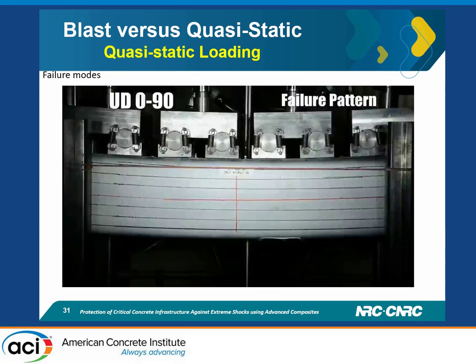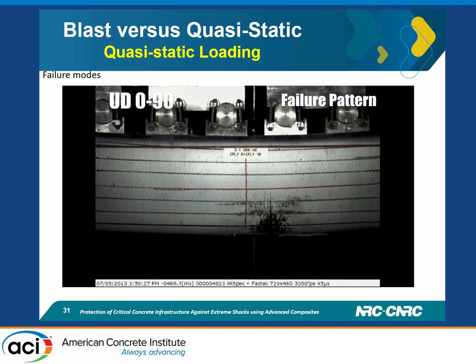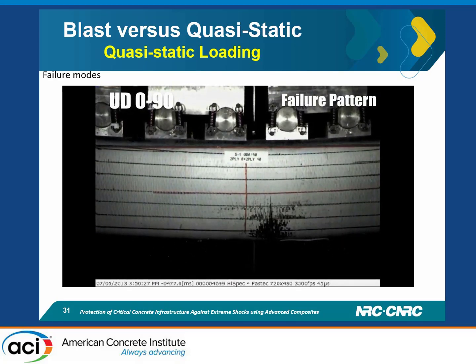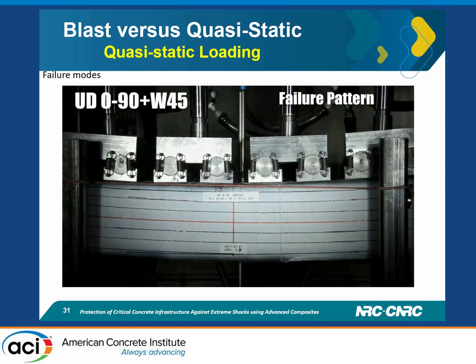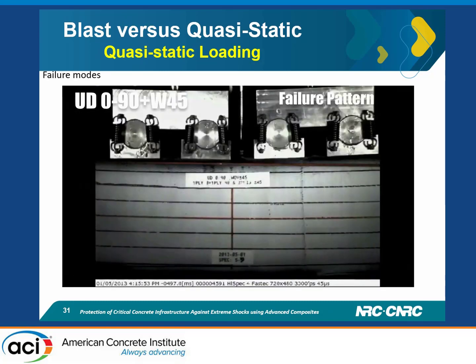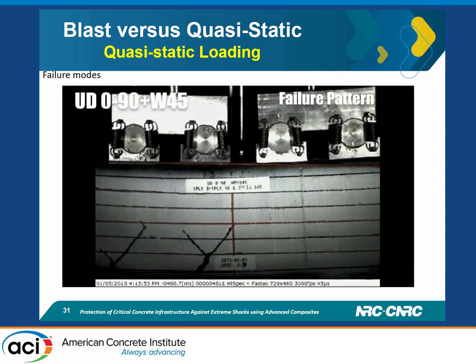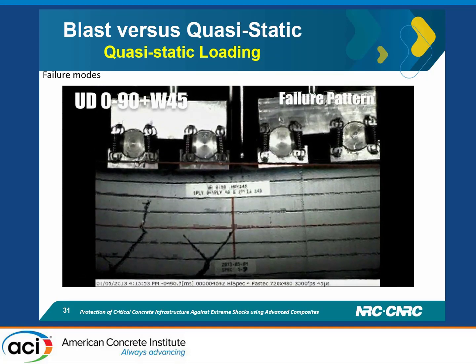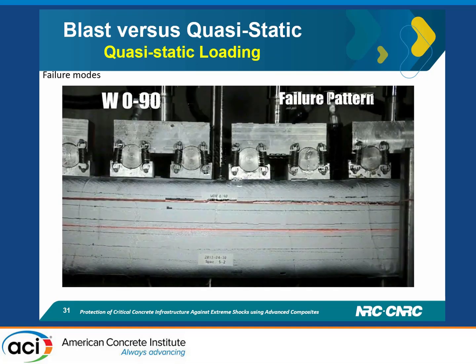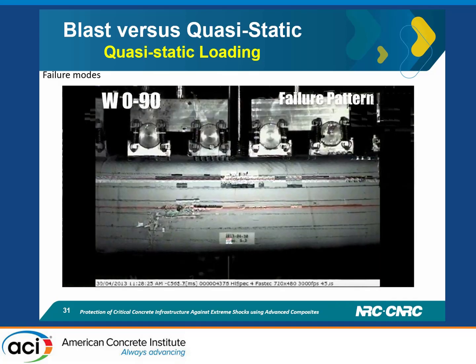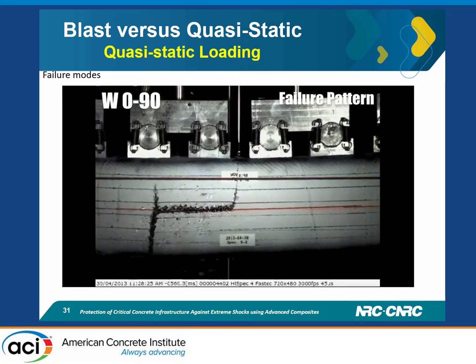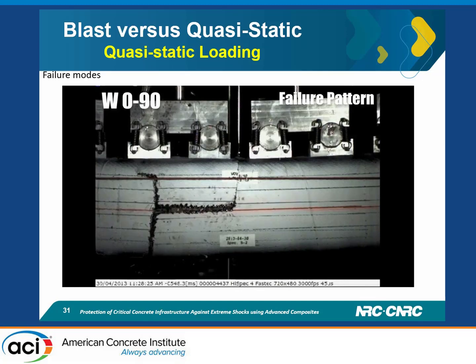Here is a video which shows you the differences in the failure modes. As you can see, here is 090, here 090 plus minus 45, and the failure of the FRP is totally different. And here is woven 090, so it's again 090 but woven, and as you can see, the failure of the FRP is totally different. In slow motion we can see it better than in the shock tube.